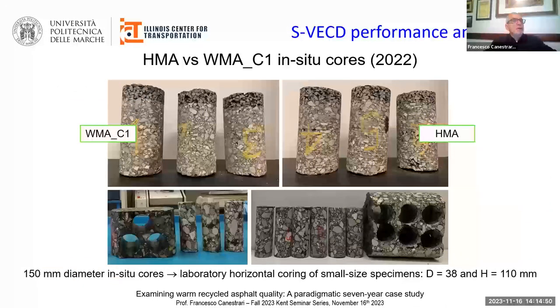In this case, we compared the performance of hot mixtures with the performance of warm mixtures prepared only with the C1 chemical additive. To this purpose, three cores with a diameter of 150 millimeters were extracted from the trial section for each type of mixture. Then, for both binder and base layers, laboratory horizontal coring was carried out to obtain small size specimens with a diameter of 38 millimeters and a height of 110 millimeters.